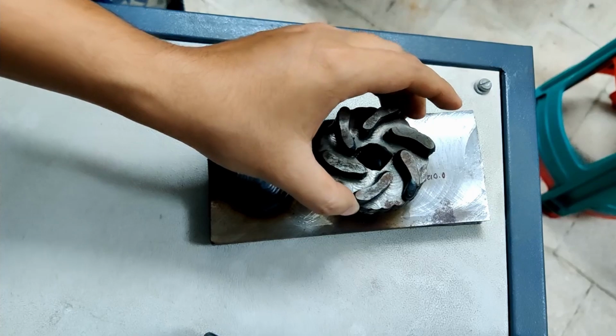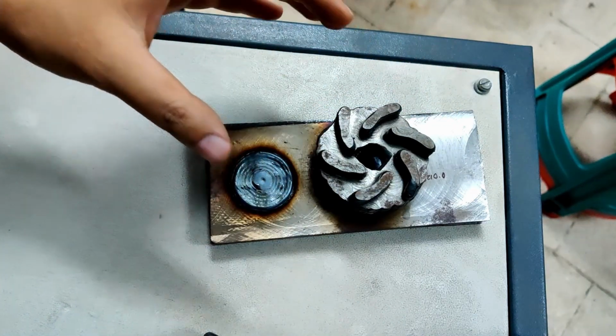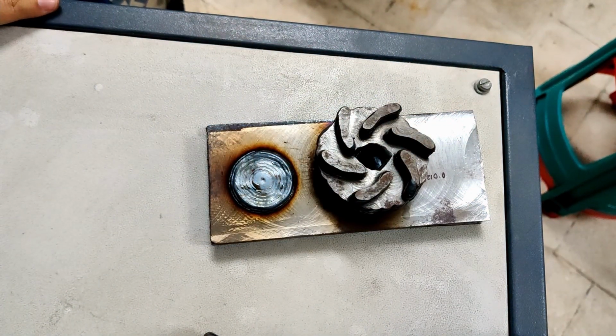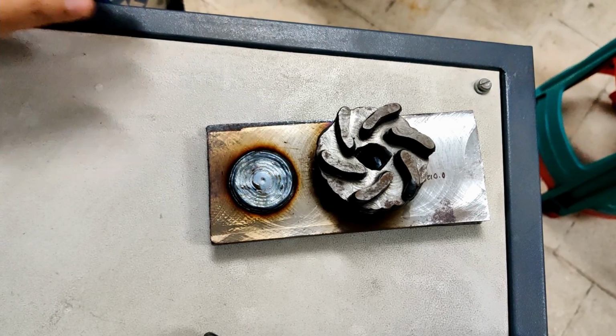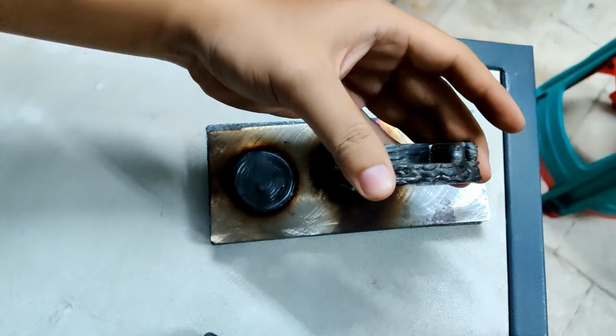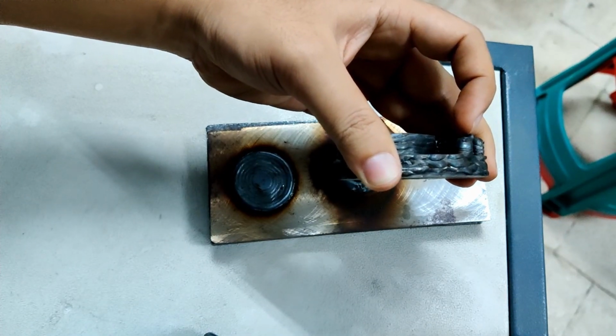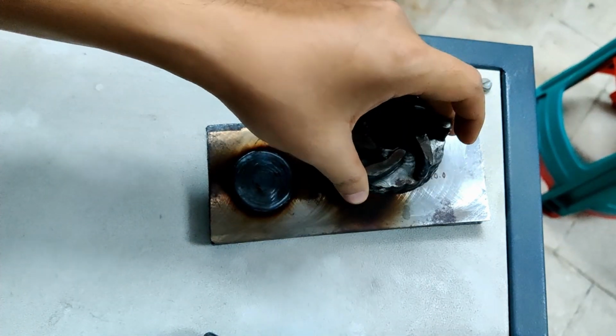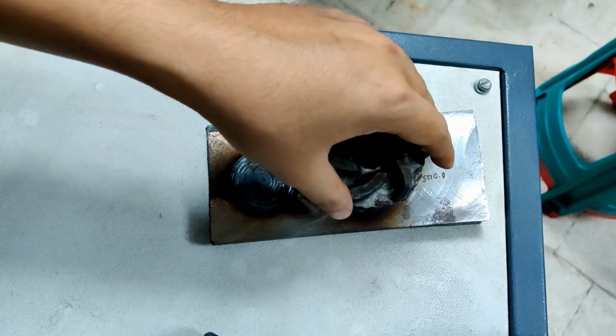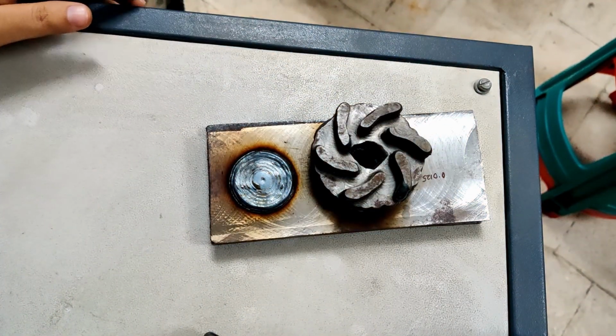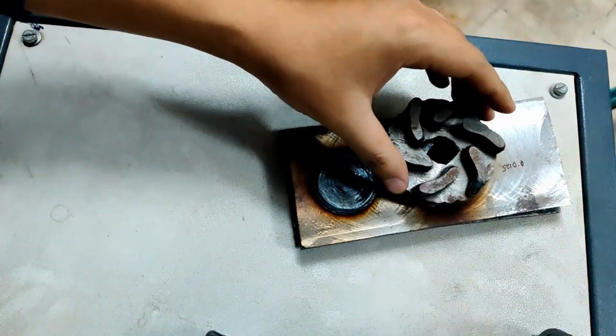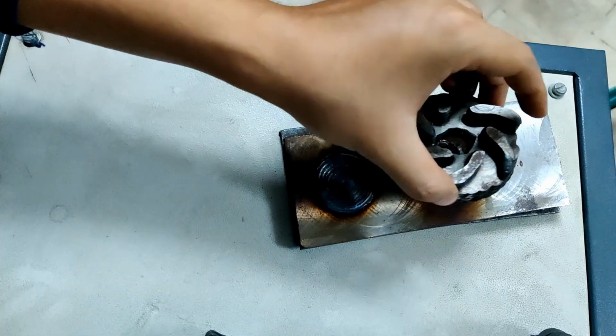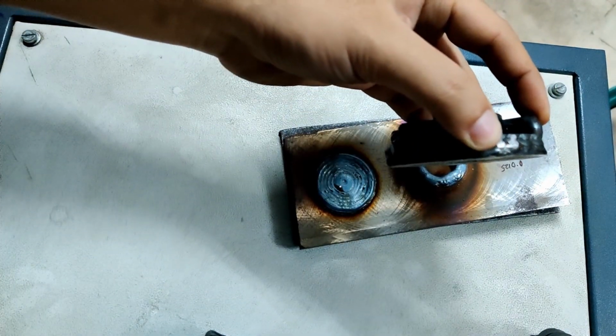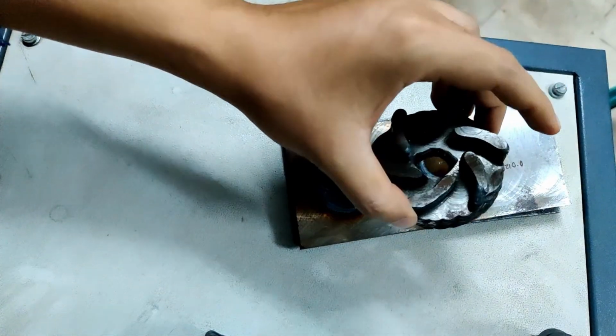To realize such a large object in other processes, say SLM or SLS, it would take around 2 to 3 hours, because its thickness is very high, like 20 mm, and to deposit 20 mm in other processes it will easily take 2 to 3 hours. As you can see, we have obtained the near net shape of the impeller through this wire arc additive manufacturing process.